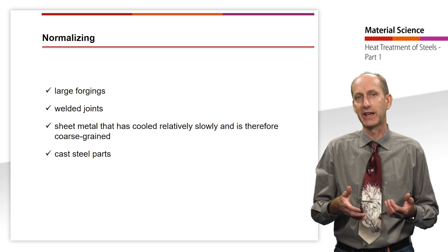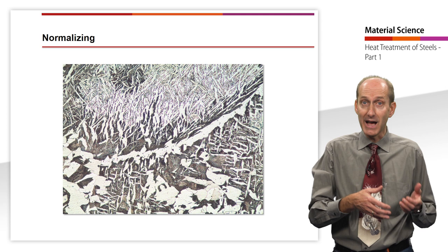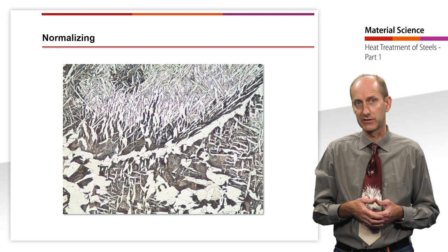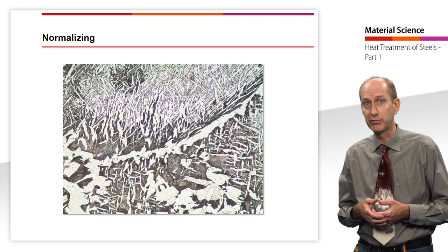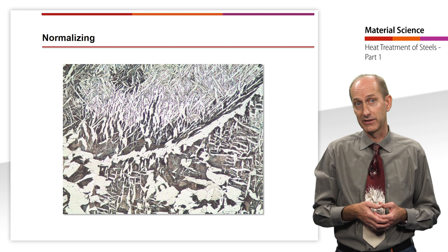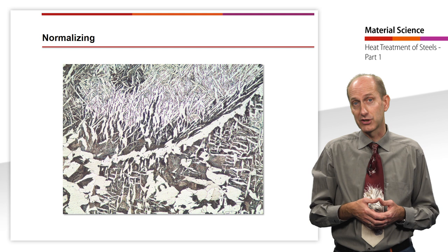During slow cooling from the gamma region, the gamma-alpha transformation normally occurs at the grain boundaries of gamma crystals. If a coarse austenitic grain is formed after heating at an elevated temperature or long holding time, and a high cooling rate is present, the gamma-alpha transformation can also occur inside the grains. The resulting microstructure is called Widmanstätten structure, or overheating microstructure.